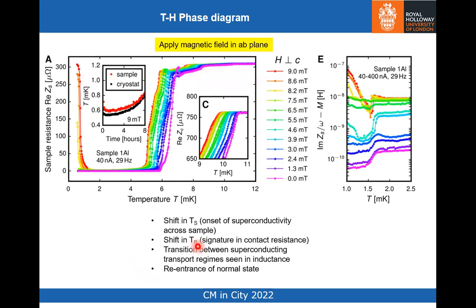So now what we want to do is explore the phase diagram with magnetic field. So we're looking here at the real part of the sample impedance as a function of temperature in different magnetic fields. So what you see is the following features. There's a shift down in the sample transition temperature. There's also a shift down in this feature TB, which is seen only in the contact resistance. There's a transition between different superconducting transport regimes at 1.5 millikelvin in the sample that hardly shifts at all with magnetic field. And then there's a re-entrance of the normal state.